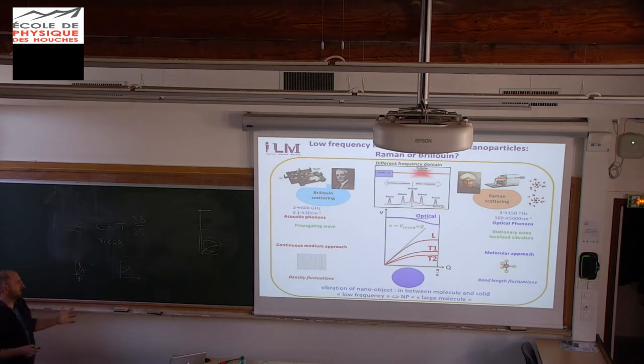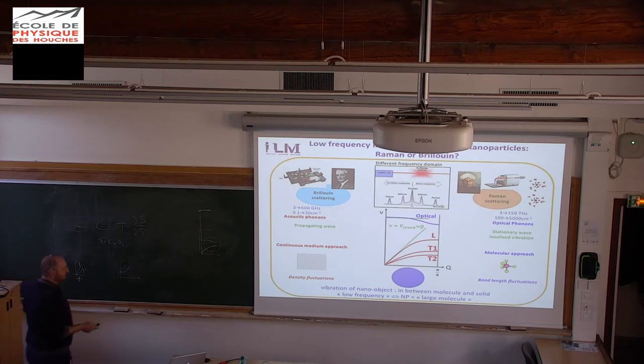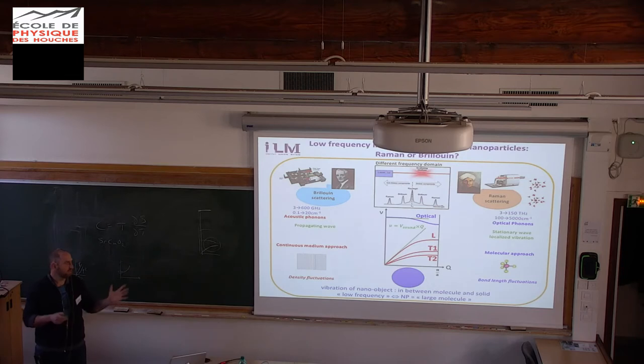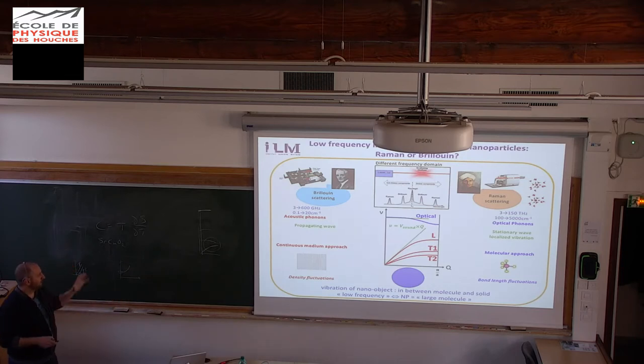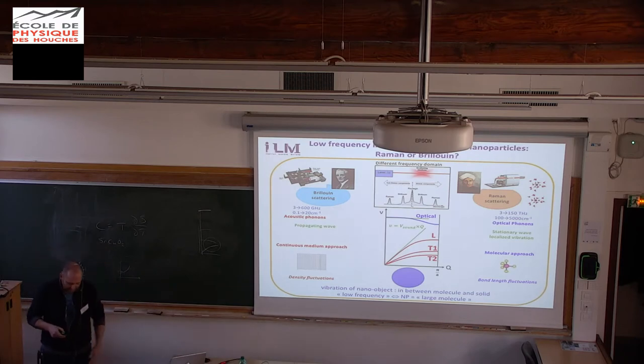And this gives me the opportunity to discuss a little bit the difference between Raman and Brillouin. What are the vibrations of nanoparticles? Is it Raman or is it Brillouin? You all know that the main difference between both techniques is just the frequency range. With Brillouin, you are down to 600 gigahertz. And in Raman, you are higher than 3 terahertz, I would say.